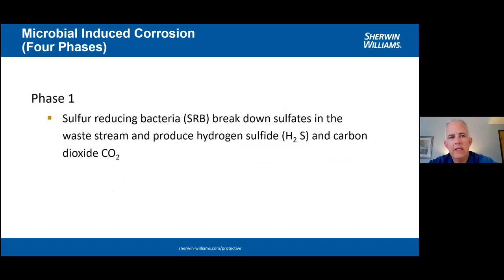So the four phases of microbial-induced corrosion. Phase number one, we have sulfur-reducing bacteria. It breaks down the sulfates in the waste stream. And this is where the hydrogen sulfide gas and the CO2 gas are generated. They produce it. These sulfur-reducing bacteria, again, are the source of the hydrogen sulfide gas that we deal with in our systems.